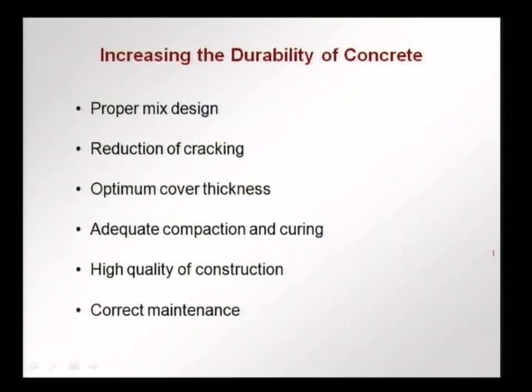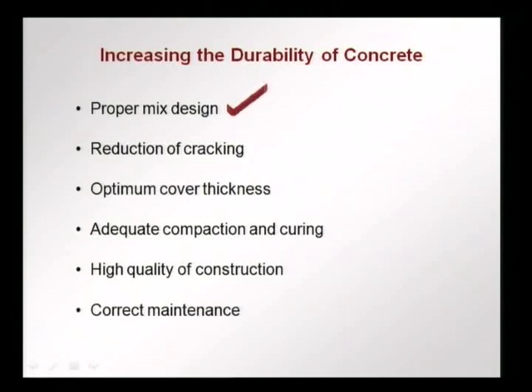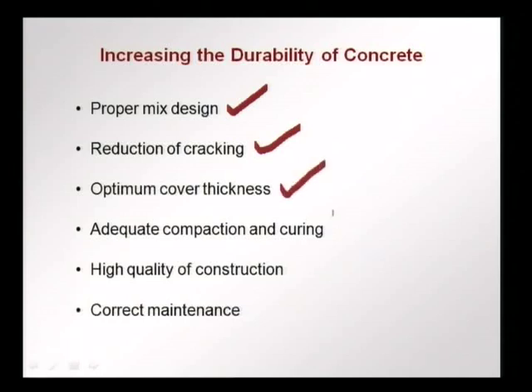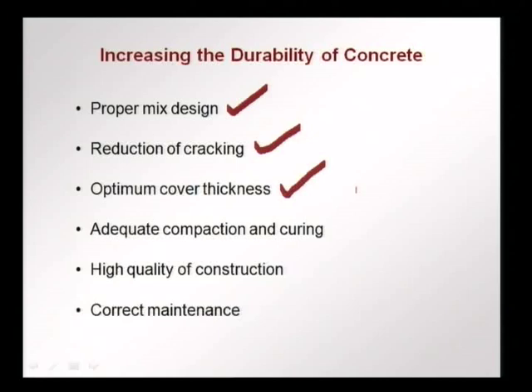To conclude, increasing the durability of concrete requires: proper mix design with an appropriate choice of components and low water-cement ratio for a compact concrete; minimizing cracking from shrinkage, improper curing, and excessive loads with crack widths as small as possible; and an optimum concrete cover — sufficient to prevent oxygen, chlorides, and carbonation from reaching the steel, but not so excessive that the unreinforced cover cracks by itself.